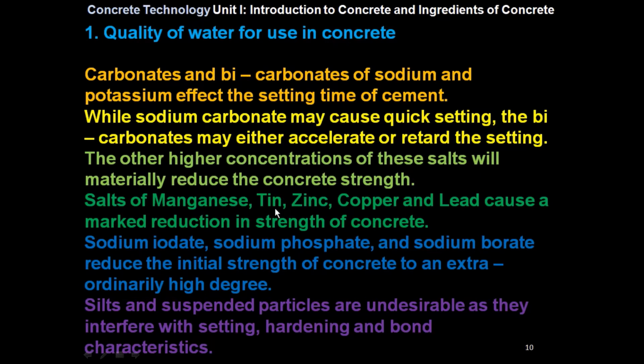Salts of manganese, tin, zinc, copper and lead cause a marked reduction in strength of the concrete. Sodium iodate, sodium phosphate and sodium borate reduce the initial strength of concrete to an extraordinarily high degree. Silts and suspended particles are undesirable as they interfere with setting, hardening and bond characteristics.